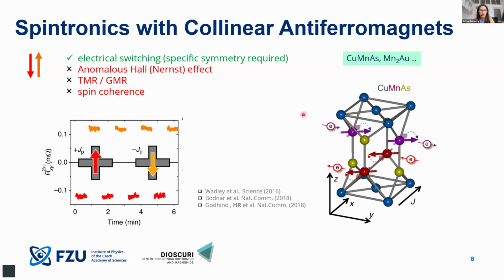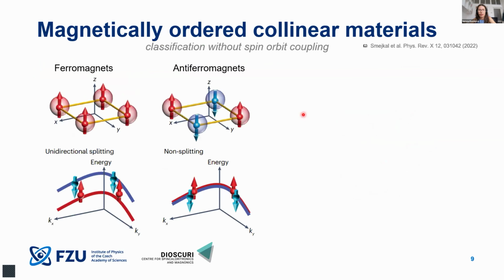So this was a small recap of spintronics with antiferromagnets, or with what I understand as antiferromagnets. And when we now stay in the realm of the collinear systems, I already get to the slide which you saw a few times during this workshop. Very quickly to recap: when we forget about spin-orbit interactions and look at the most simplified model, ferromagnets are the systems which we like because they exhibit a large splitting between spin up and spin down in the electronic bands. In collinear systems such as copper-manganese arsenide, which I showed before, the spin up and spin down bands are degenerate, therefore not allowing for effects like the anomalous Hall effect, but nevertheless allowing for many other interesting physics, which I mentioned on the previous slide.